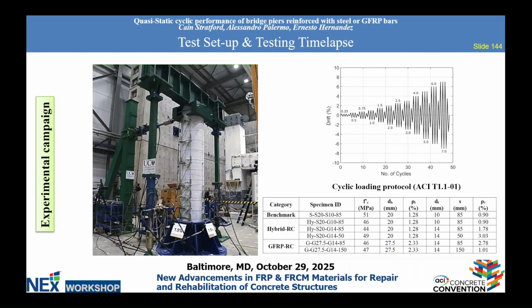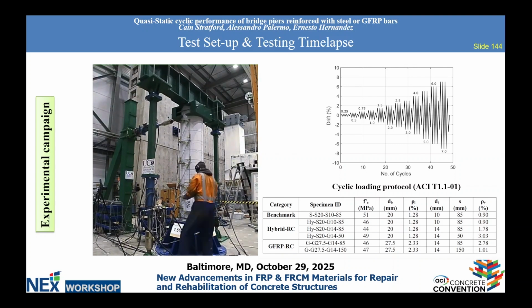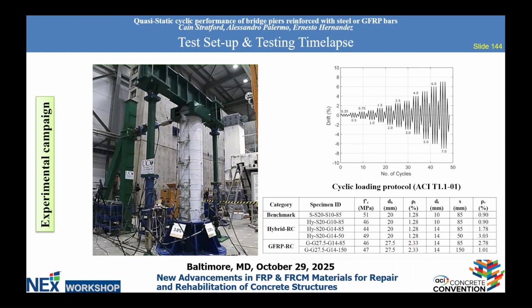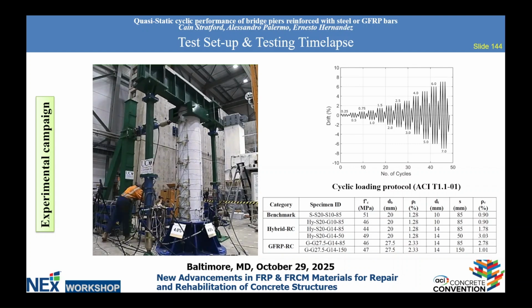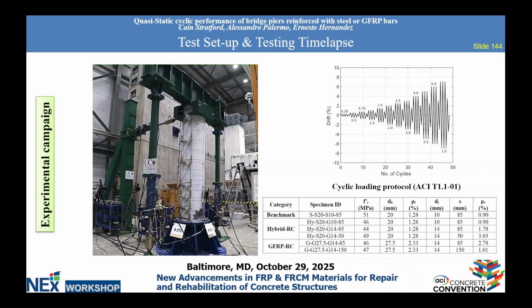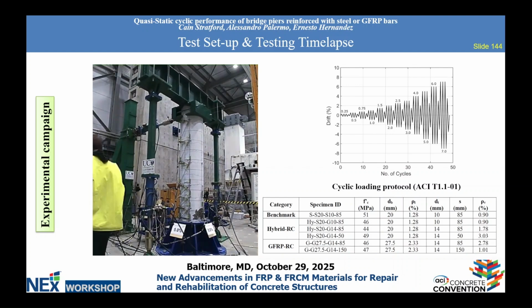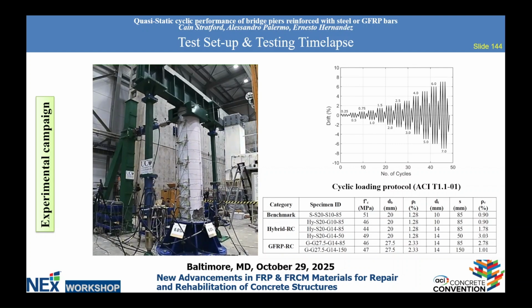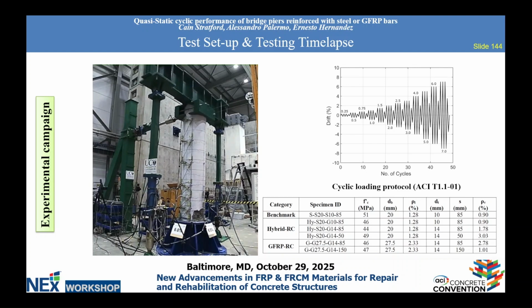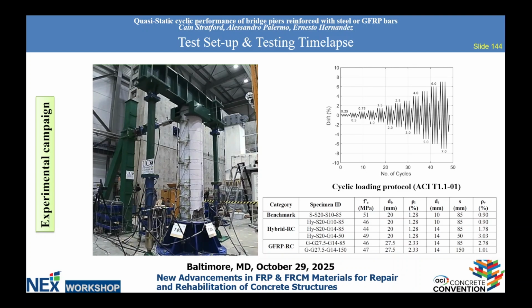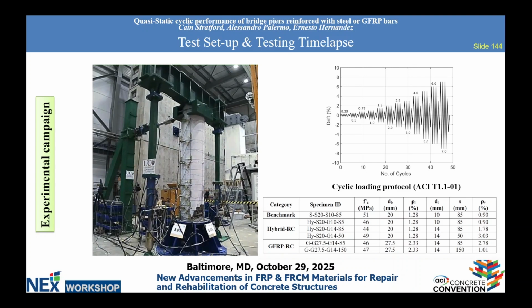We did quasi-static cyclic tests, and you can see that we didn't use a concrete footing. We used this steel footing, which was bolted with 2 halves. The reason is that I had 2 other PhD students, and we tested 20 other columns, and by not casting the footing, it was a big saving. We monitored all the displacements because we wanted to make sure there was no slip between the grout and the footing. We looked at the hybrid, we kept the same spacing as the benchmark, and then we increased the diameter of the bars, and then this is the full GFRP.